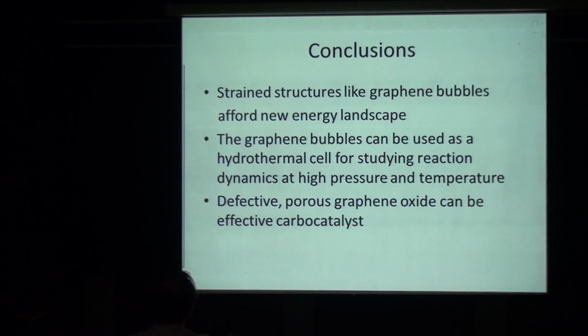The graphene bubbles can be used as a hydrothermal cell for studying reaction dynamics at high pressure and temperature. This is very interesting. Now we chemists are scratching our heads to see what kind of new chemistry we can uncover in this condition. And the more defects, the better. Porous graphene oxide can be an effective catalyst. It's a new term we call the carbo-catalyst, the carbon catalyst. The carbon catalyst may be very good. It can replace all the expensive platinum metal catalysts, for example.